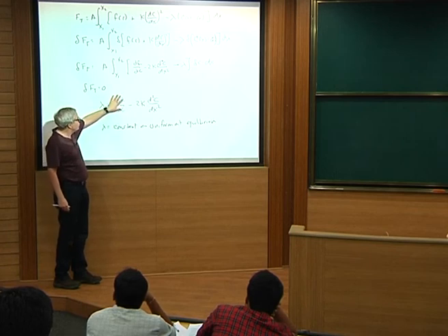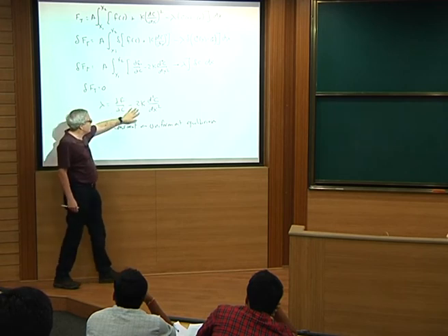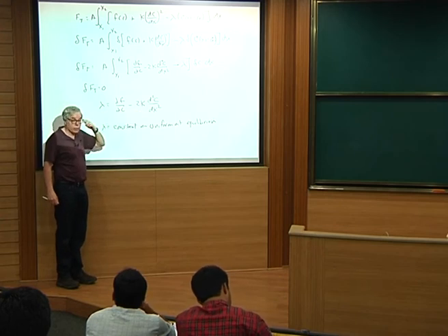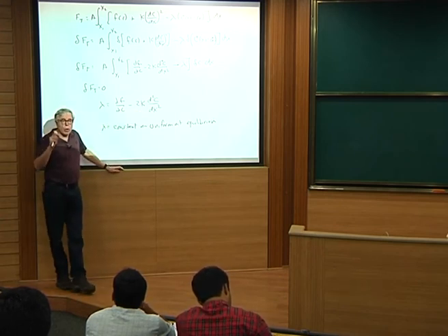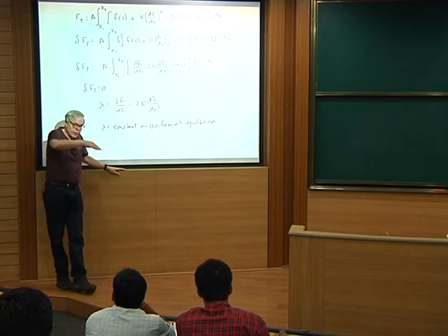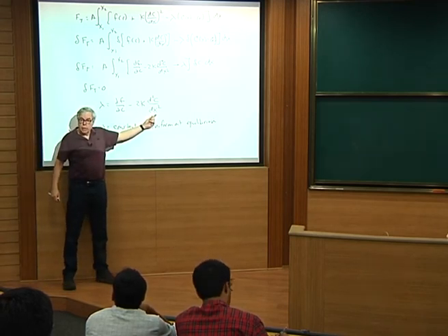And it's because it includes a term that looks like dF/dC, which looks like some chemical potential terms, but it has this gradient term, okay? The term involving the second derivative. Remember when I gave this argument about whether gradients should be important? Remember I said that if there's some curvature in the free energy, if there's some curvature in the composition, it should change the chemical potential? Curvature in the composition.